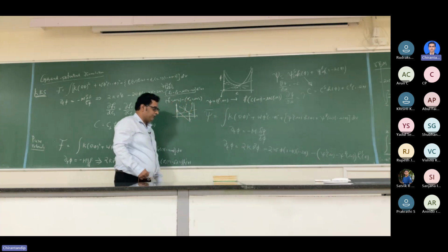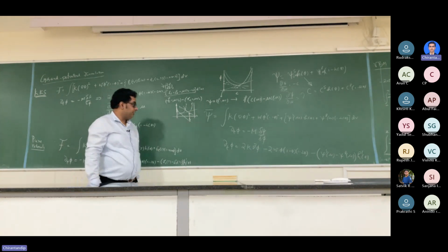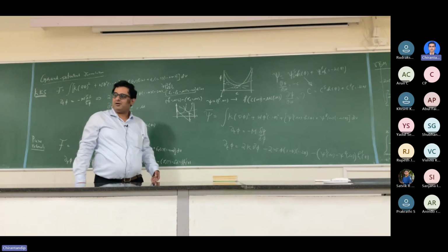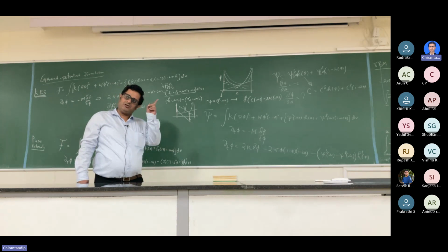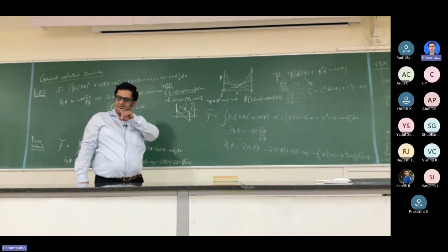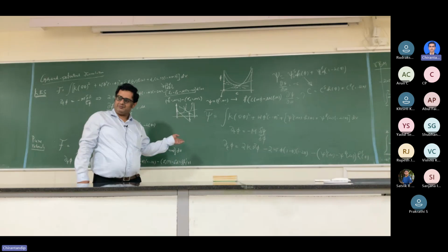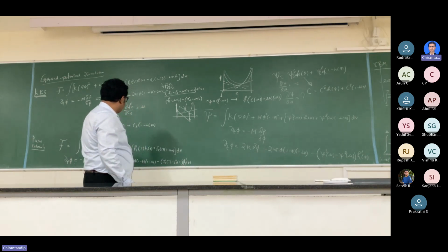Okay? Now the only question that remains is, you can't solve this equation. Why? So this is the mu sitting there. You need an evolution equation for mu. Alright? But that is, as you all know, going to come from a conservation equation, just as you required an energy conservation equation for the temperature T. You started from dou E by dou T is equal to del dot K grad T. Create the evolution equation for the temperature T. So you start from a conservation law. Here also you will start from a conservation law, which is the mass conservation law, which is going to be the following.